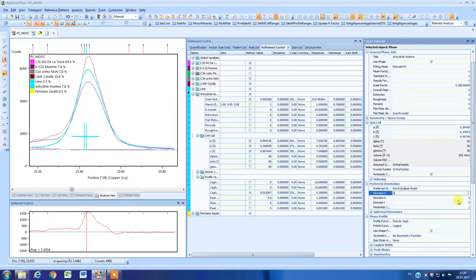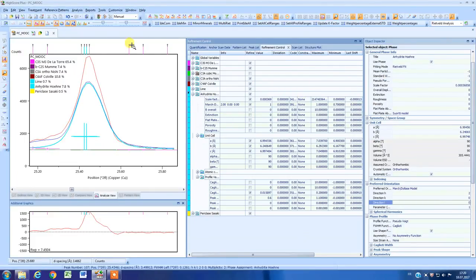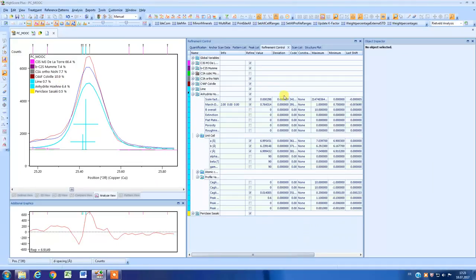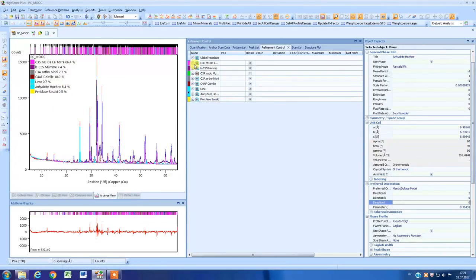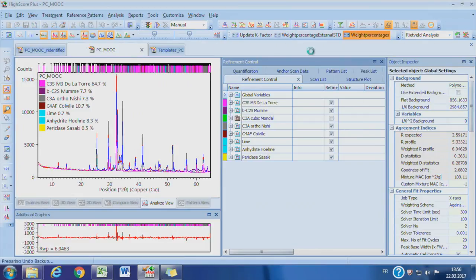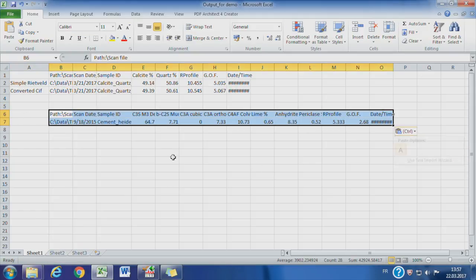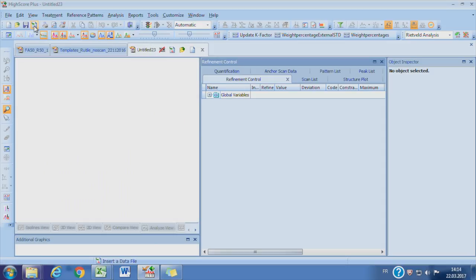A larger phase that can easily have preferred orientation is the anhydrite. Do the same for the preferred orientation of anhydrite for the 2-0-0 direction. After refining, there is some improvement for the goodness of fitting and the weighted R profile. The RWP value is now 6.9463 as shown in the additional graphics. By pressing the button with the percentage symbol, you will have the quantitative data output in the XLS file in the default HighScore folder. Note that here we do not consider amorphous content in the anhydrous cement, as it is the same one with no amorphous SCM added.